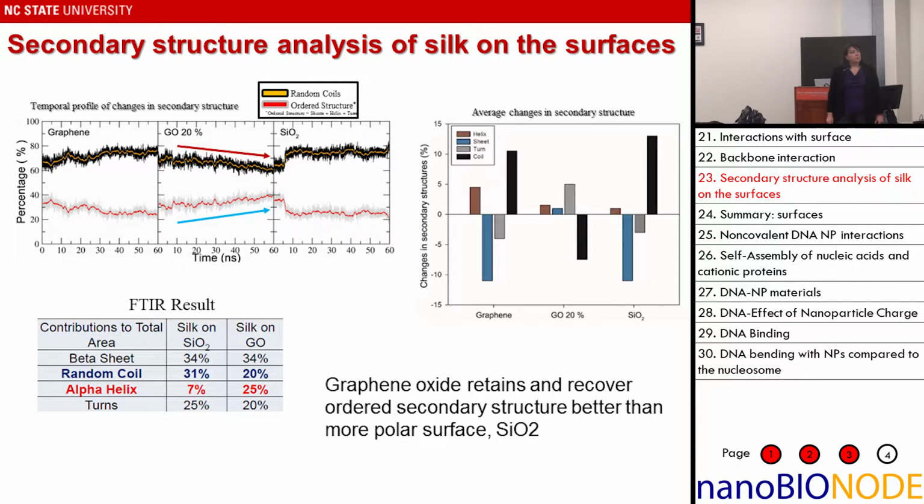So in general, we got interesting results. We also see with this time frame that we are recovering. Compared to our original structure, we see the rearrangement and recovery of the secondary structure elements. That's why it's increasing. So the interactions of the backbone with the surface lead to recovery of this type of elements. The only difference we saw between these 2 interactions is that the secondary structure is very different because of the way the backbone and side chains interact with the surface, and that relates to the distribution of the polar groups on the surface.